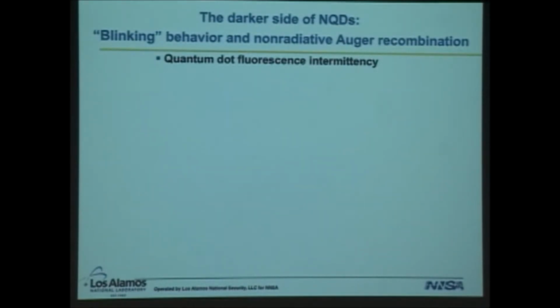So, the darker side of nanocrystal quantum dots. I'm focusing here on 2 unfortunate attributes of quantum dots. One, their blinking behavior. At the single particle level, if you shine a laser at them and you observe their emission, you will see that the emission is not constant. The particles will emit light, but then turn off and then turn back on in a random fashion. And so for certain applications, for example, single particle tracking in biology, using these as single photon sources, blinking behavior is obviously unwanted. And simply put, it's a non-radiative process that we could do without in many cases.